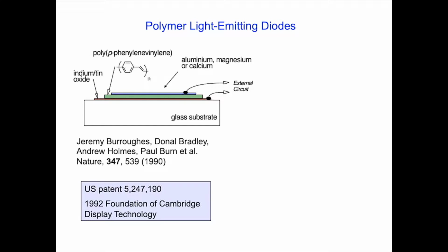I mean, a number of groups in different ways, going back 25, 30 years now, appreciated that as soon as we could process these materials, we could have a go at making devices. And in some cases, the devices are amazingly simple. So the structure here, where we've got a glass sheet with a transparent indium tin oxide metal, we then spin-coated a layer of green fluorescent polymer and then evaporated a top blue layer of a low work function metal.